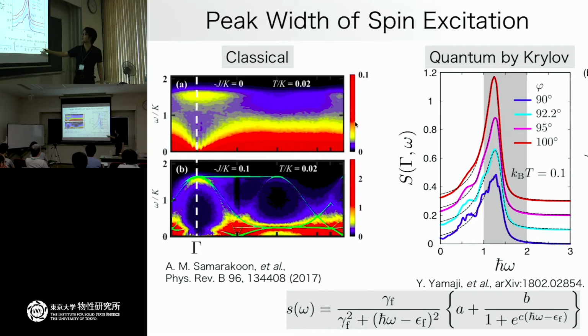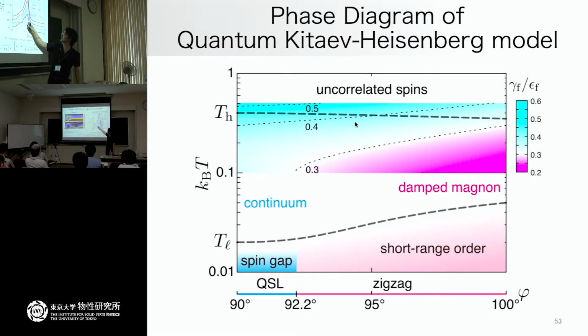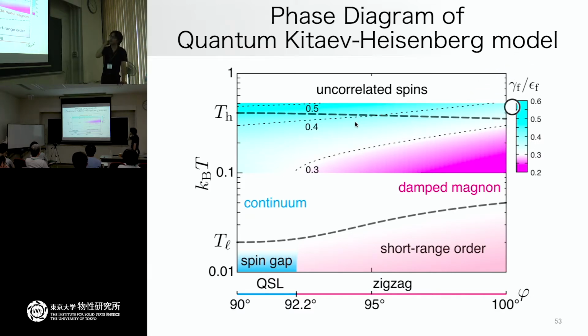Here I used this kind of fitting curve to extract the width and the peak energy. Then if you take the ratio of the peak width gamma over the peak energy epsilon, we can make this kind of color plot on top of the two energy scales, the temperature phase diagram of this system.